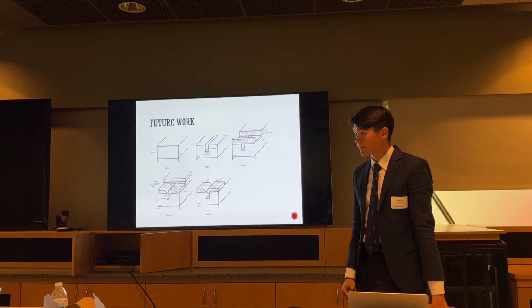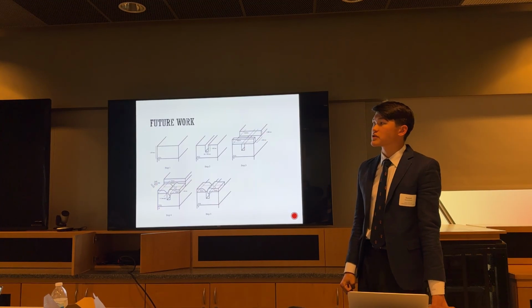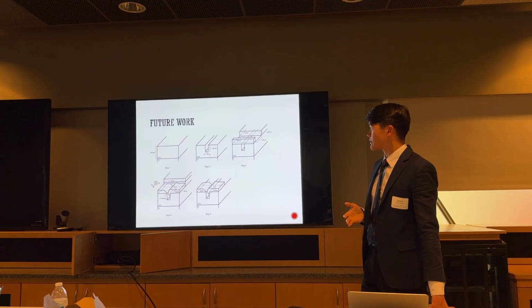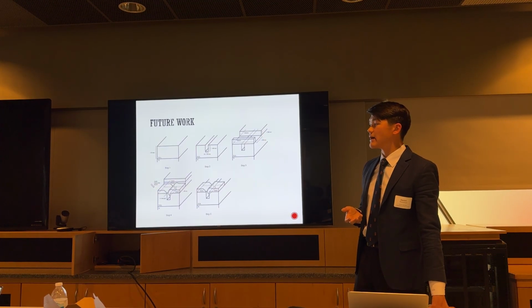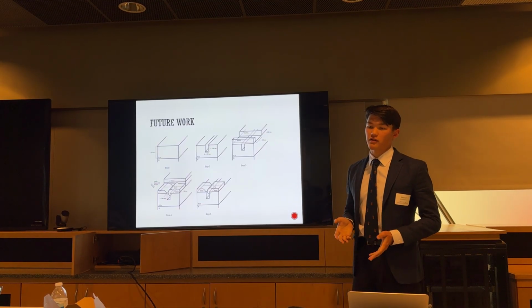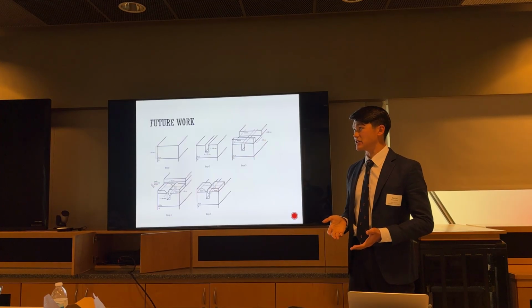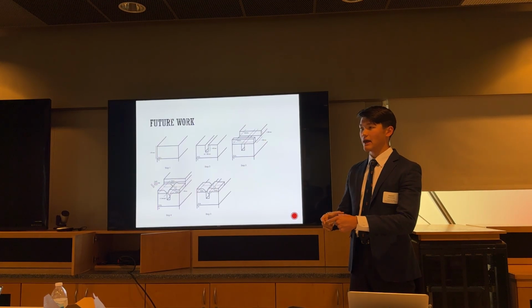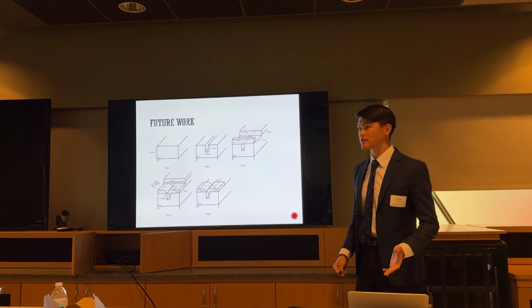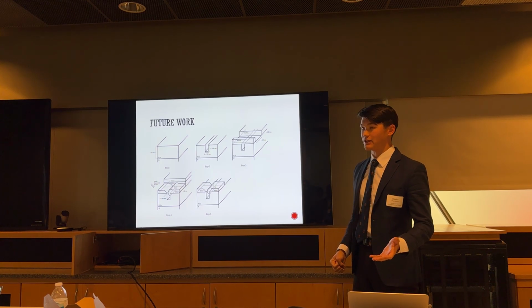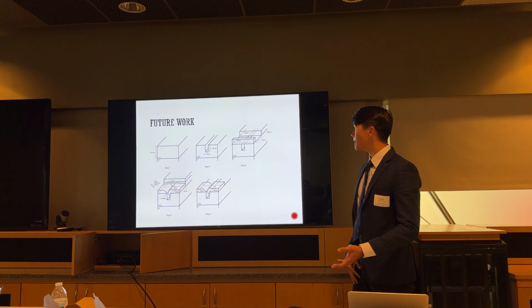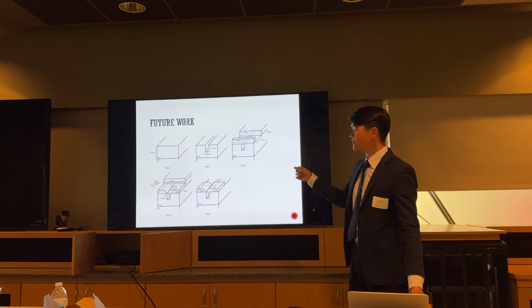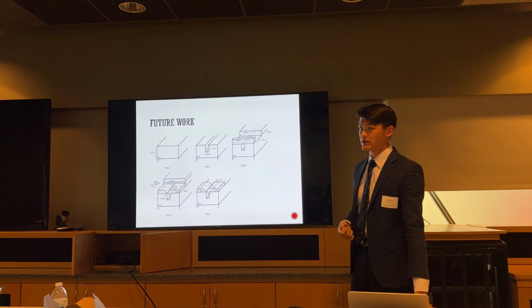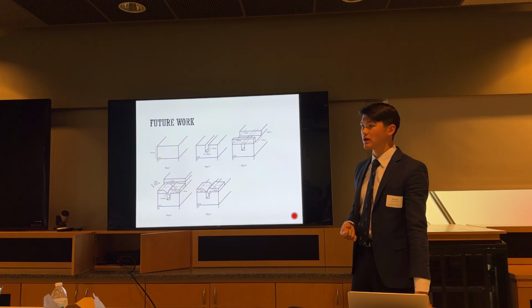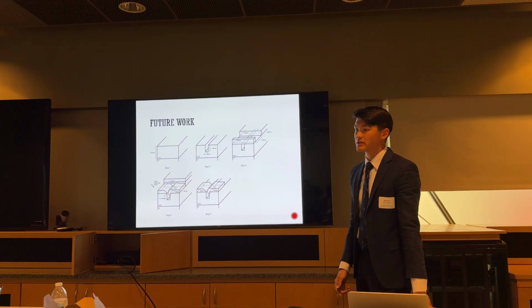What is the major advantage of your technology compared with standard lithography, like photolithography patterns? Electron beam lithography is better in that you can create smaller features, because photolithography is limited by the wavelength of light. The other main advantage is that with photolithography, you have to make a mask for everything you make, and we are doing experimental research, not mass manufacturing. If we wanted to do photolithography, we'd have to make a mask first, and that requires electron beam lithography. And ytterbium fluoride itself is a good material, and we also wanted this project to be a chance to investigate ytterbium fluoride as an electron beam resist. We basically just had the better equipment for electron beam lithography.